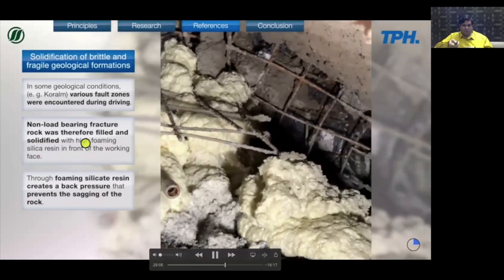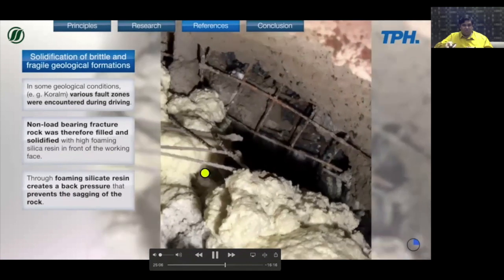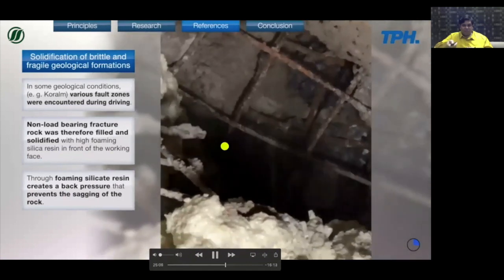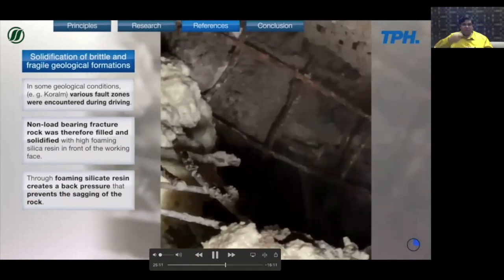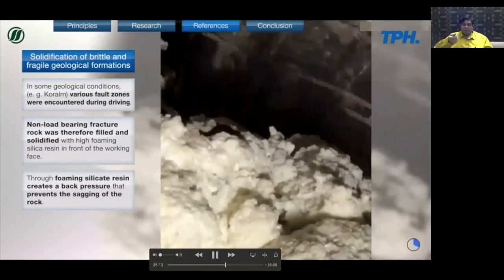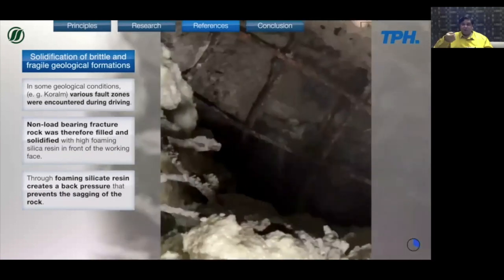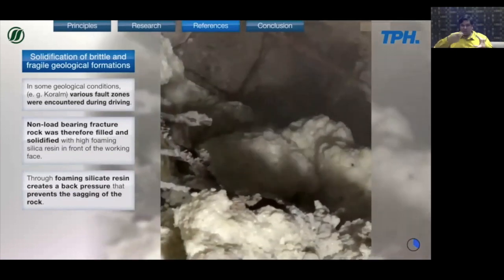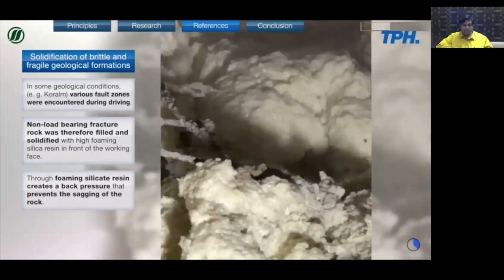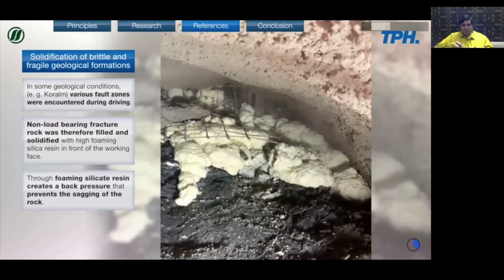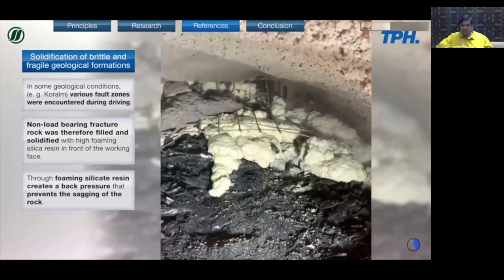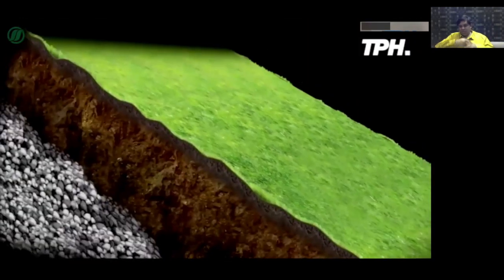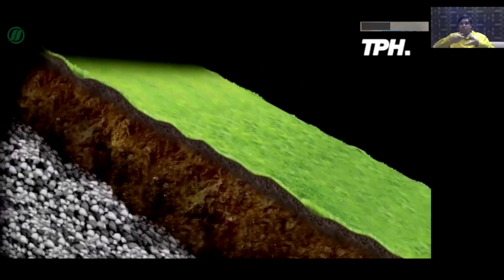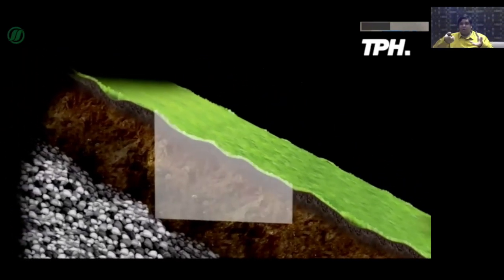So what was done was that silicate foam was injected. This silicate foam material has an expansion factor of about 70 to 80 times its initial volume. That means 1 liter would make almost 70 to 80 liters of foam. Okay, so you can see that material was injected into it. It expanded and it holds and consolidates the entire rock face together.